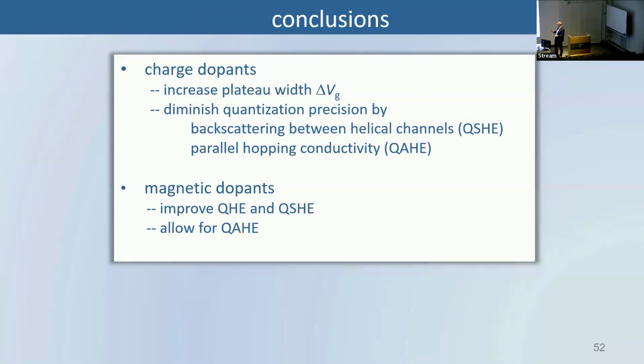So this brings me to conclusions. Charged dopants increase plateau width, which is good, but diminish quantization precision by backscattering between helical channels in the quantum spin Hall effect. And also, these impurities produce parallel hopping conductivity in the quantum anomalous Hall effect. Magnetic dopants improve the quantum Hall effect and quantum spin Hall effect. In this case, it is by killing the Kondo effect. And magnetic dopants are crucial for the quantum anomalous Hall effect. Due to magnetic dopants, we have the quantum anomalous Hall effect.